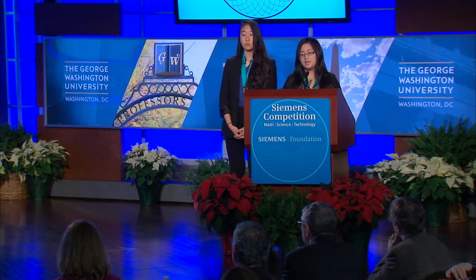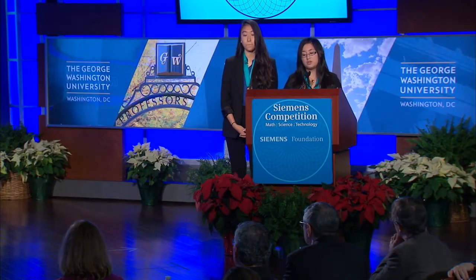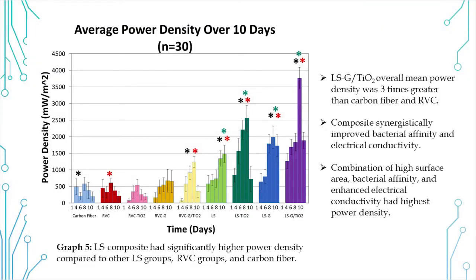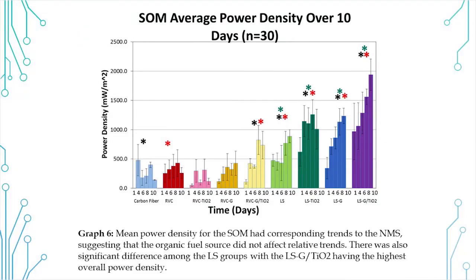Now for the power density, which was used with projected surface area, the results also correlated with the power output, in which between the structural groups, the loofah sponge was the most effective anode material compared to the RVC and carbon fiber. And this can be attributed to the SEM results, in which the loofah sponge had the highest surface area, which will allow for more space for bacteria to adhere on and for more electrons to be collected for higher power density. Interestingly, between the surface coatings, there was no statistical significance between the titanium dioxide and graphene, despite the fact that graphene has higher electrical conductivity.